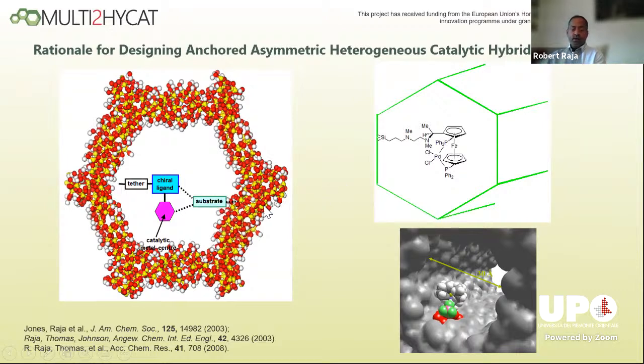The advantage here is when your substrate now approaches this catalytically active site, it now sees many kinds of interactions. So it sees an interaction with your metal center if it's present, or it sees an interaction with your organocatalytic center. And if both are present, it has a simultaneous influence on both these active centers, but also on the curvature of the internal pores of your catalyst. So what is shown here on the right is really one of these anchored ferrocene systems within a pore architecture, which has a pore aperture of about 30 angstrom. So if you choose a substrate molecule, which is quite bulky in this particular case, this can approach the active site only in a particular fashion.